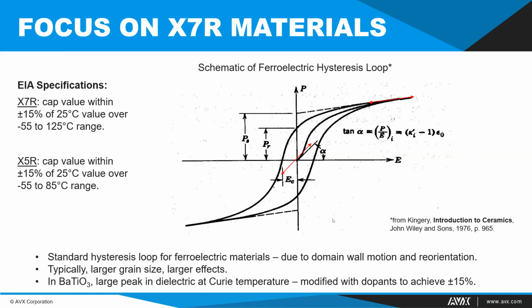I've borrowed a diagram of a ferroelectric hysteresis loop from my favorite reference from the old days, and that's from Kingery's Introduction to Ceramics here. And you can see that the relationship between both the polarization and therefore the dielectric constant of a device actually changes with the field. The slope of the PE curve is actually what's represented as the dielectric constant. So when we apply a field to the device, we can see that the slope of that line changes as we march along it. And if we were to put bias on the device, we would actually move that slope along this line that's represented in the upper right-hand quadrant.